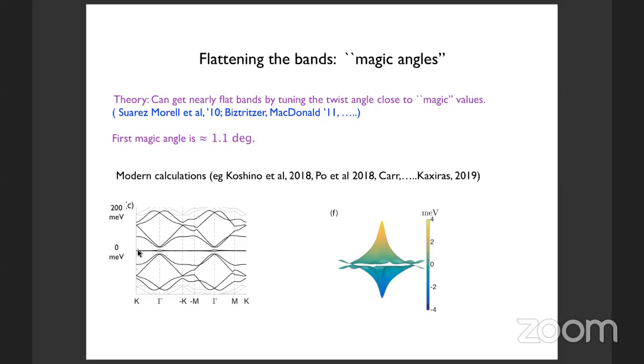I've shown here a reproduction in some modern calculations found in some subset of these papers. You see the bands plotted inside this mini Brillouin zone as a function of momentum. On this scale, the vertical axis is 200 millielectron volts, and you barely resolve the width of these bands right in the middle. So these are the narrow, flat bands. That's where all the interesting things are going to happen.